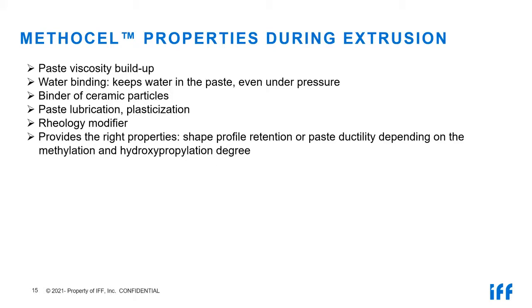And of course, I want also to address the topic of shape retention and paste ductility. Both are impacted heavily by the substitution of the cellulose chain, which means, translated into normal words, it depends on the so-called chemistry of the METHOCEL. So there are grades where the paste ductility is high, and there are grades where the paste ductility normally is lower. Then the stiffness is higher. It has advantages and disadvantages. So it is always a question to find the optimum for your recipe and what your individual conditions really require. Next slide, please.